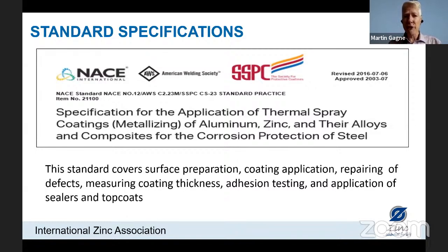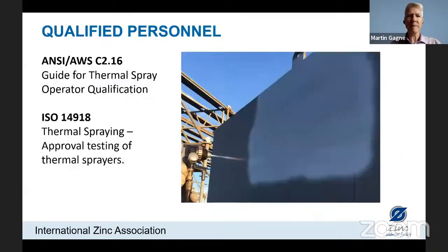So this is for the application of thermal spray coatings of aluminum, zinc, and their alloys, and composites for the corrosion protection of steel. So this covers all aspects of the process: the coating application, surface preparation, repairing, measuring, adhesion testing, and then painting and top coating. There are other standards as well to make sure that the operator is qualified. Another American Welding Society standard, C2.16, Guide for Thermal Spray Operator Qualification, and an ISO standard, approval testing of thermal spraying. Here, a number of sample coupons are sprayed, the roughness of the surface is measured, the thickness of the coating is measured, and then you can have an examination and be approved as a qualified thermal sprayer.